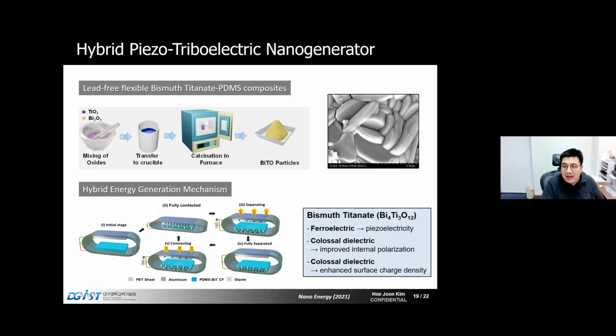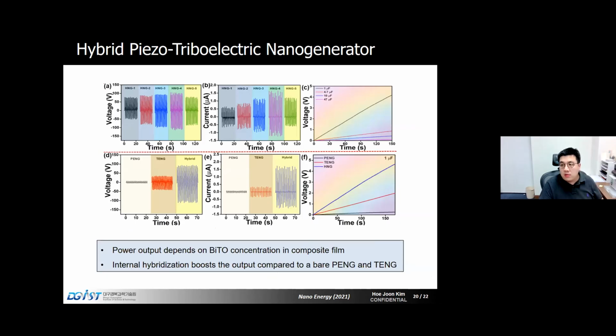So when they make contact, this composite film will get pushed or strained or stressed. And when they get separated, there'll be this generation of triboelectric energy. So we did this somewhat internal hybridization of two different techniques. And we changed the weight percentage of this bismuth titanate nanopowder. And we built a comparable single piezo device and also a tribo device. And we were able to find out that this internal hybridization resulted in about a twofold improvement in voltage and also a much larger improvement in current.